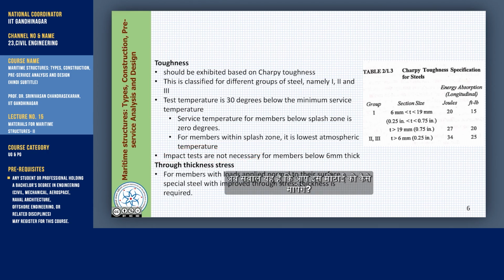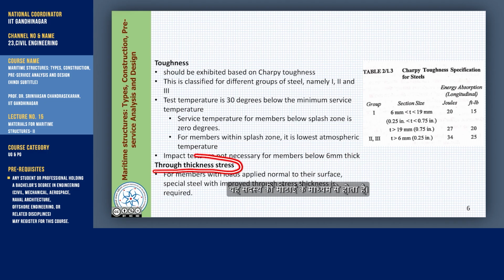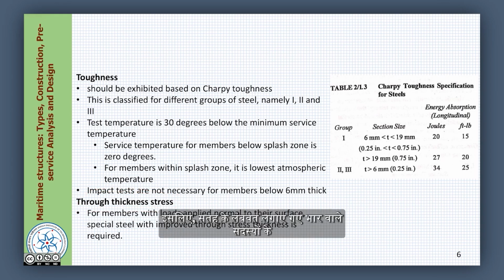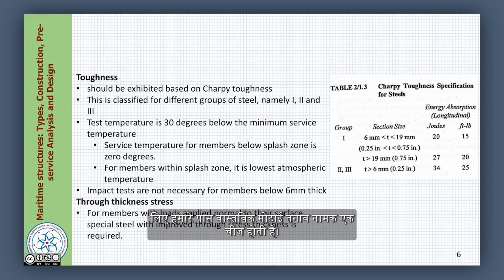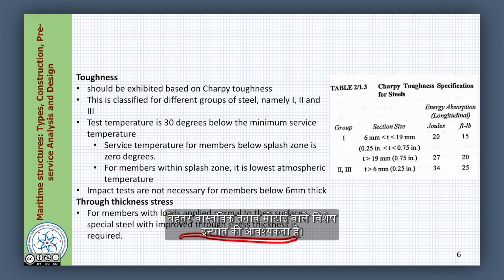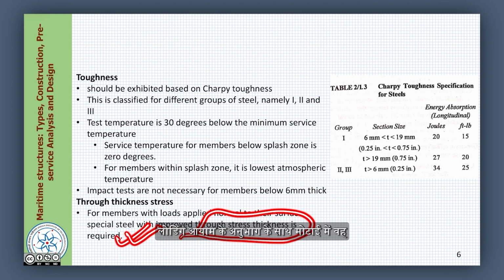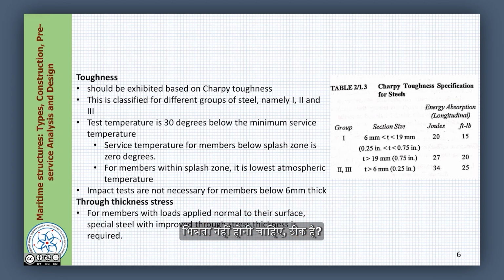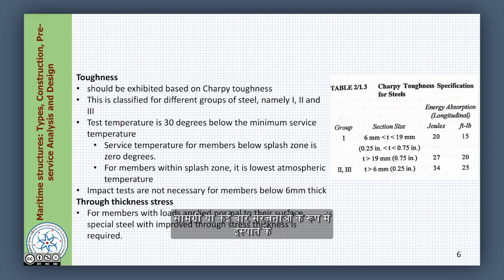Now the question is, how do you measure this thickness? The thickness is not on the surface, it is through the thickness of the member. So, we have something called through thickness stress. For members with loads applied normal to the surface, special steel with improved through thickness stress properties is required. You cannot have thickness variation along the section of loading dimension. So, there are very stringent requirements advocated by the international codes for steel to be used as construction material for maritime structures.